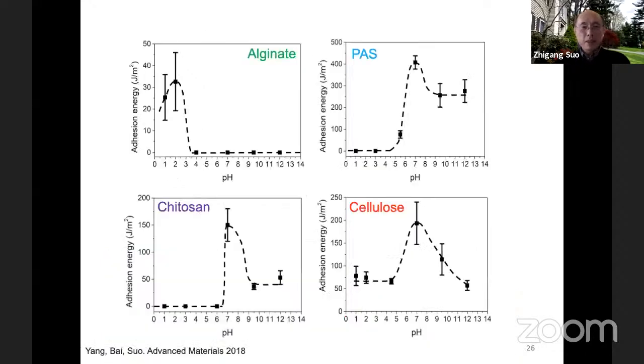Just to show not only chitosan does this, we tried a number of other gels: alginate, PAS, cellulose. They have a very similar signature peak, but the peak happens at a different pH depending on the polymer. All these numbers, you just have to do experiment. So far, we don't know how to do calculation to predict where the peak is—so you have to be a chef.